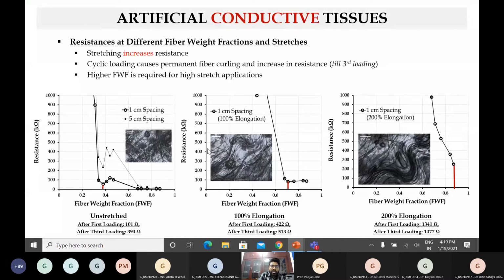The second challenge which we saw is that a lot of these soft tissues, if we use them in wearable devices, would go through not 1% elongation, but up to 100 or 200% elongation. There are a lot of moving joints in our body, which will take this entire wearable and stretch it to a very high amount of elongation. So what really happens? Does our material still hold valid for passing charge or current while that is happening? We found out that is not the case.